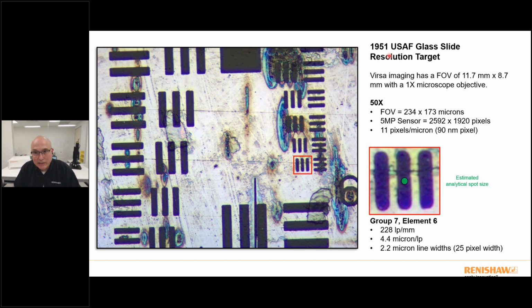So I've had this 1951 US Air Force resolution target in my bag for 20 years. And it really looks like it. It's really dirty. It's got all sorts of laser burns on it. This bar here is group 7.6. This is the smallest feature on the bar. Those line widths are 2 microns wide, and I have approximately 25 pixels across that line width. So my pixel resolution with a 50x objective on the Virsa spectrometer is very, very good. I'm getting really high spatial resolution. I can visualize things very clearly. The white light illumination is perfect, I believe. And then your analytical spot size is going to be roughly about half of that. So you're getting roughly about a 1 micron laser spot on top of there.